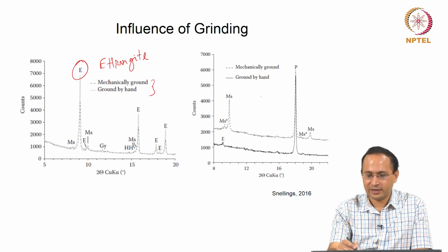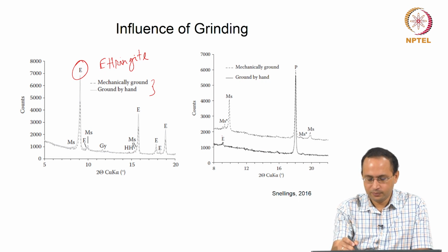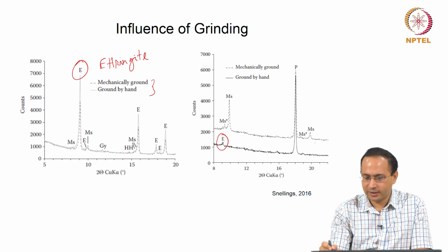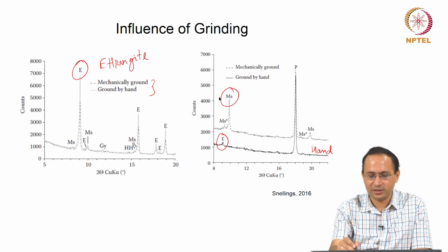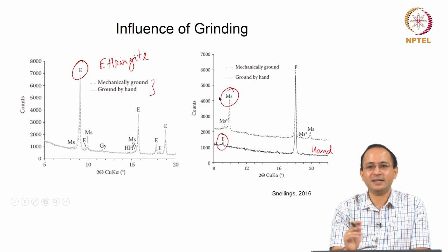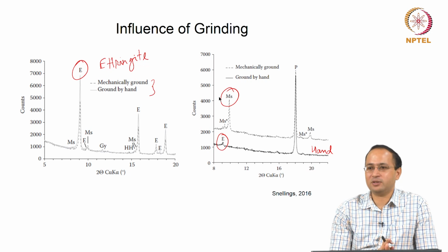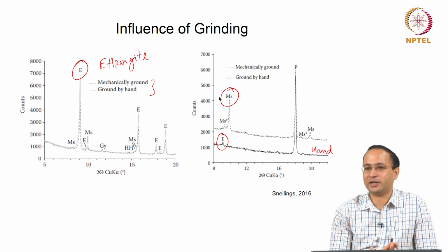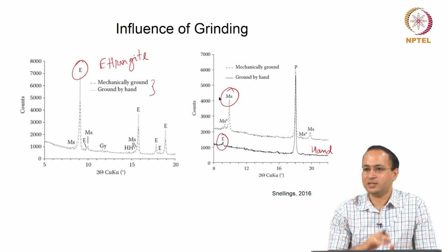Here also you see, in this case on the right plot, when you do hand grinding you have Ettringite, but when you do mechanical grinding you see a formation of monosulfate. Basically it tells you some of the phases which are present in your sample may get affected by the temperature rise during grinding.